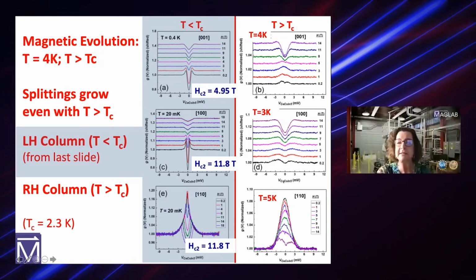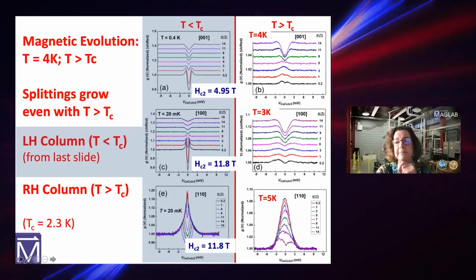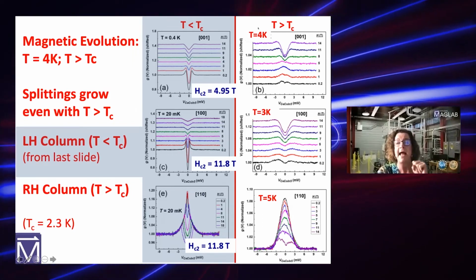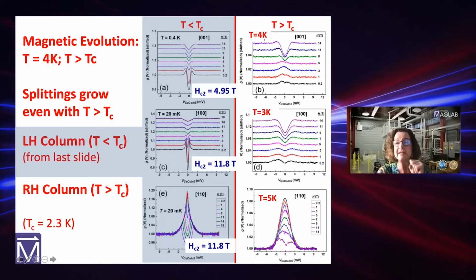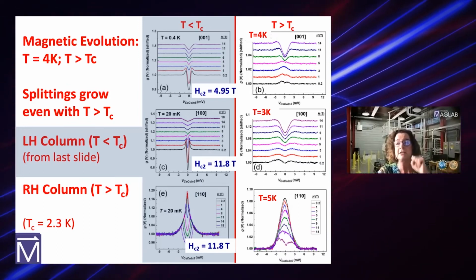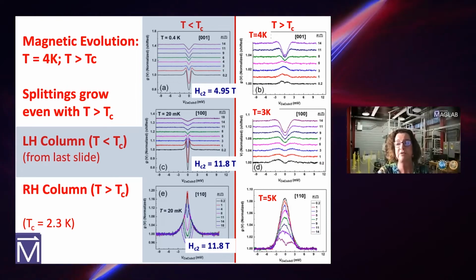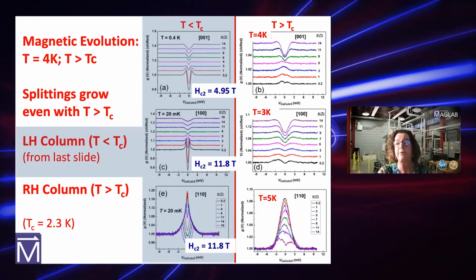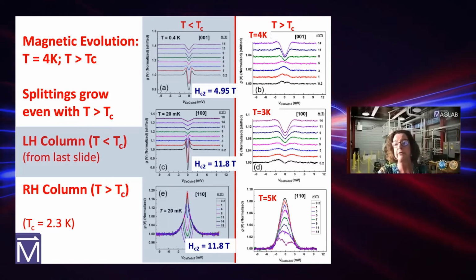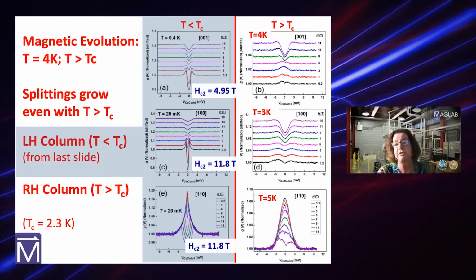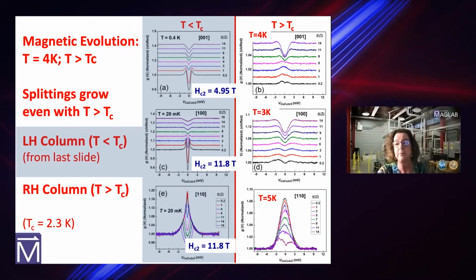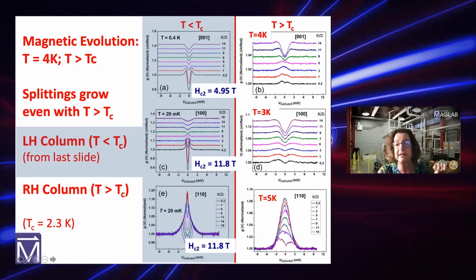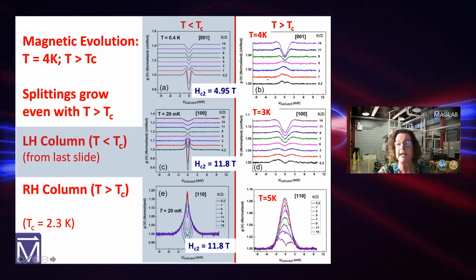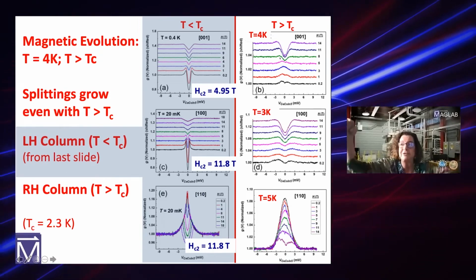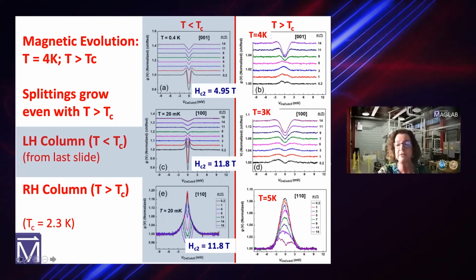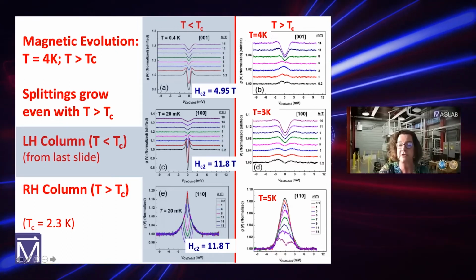Now look at these to the right here. You haven't seen these data before. These are done at 4 K. TC of this material is 2.3 K, so we're above the superconducting transition temperature. But we're in the area where there's pre-formed pairs. Both our group says that, and those other groups that I mentioned earlier say there's pre-formed pairs. And what do we see? As we increase the field, we see there's no gap, but we see some kind of a field-induced gap coming in. And that's also true. We see a splitting coming in the 110 direction.